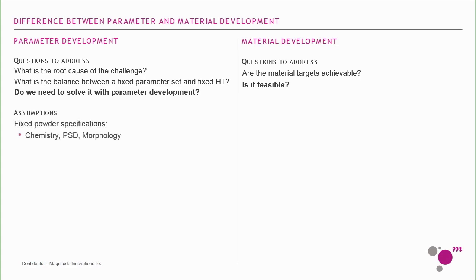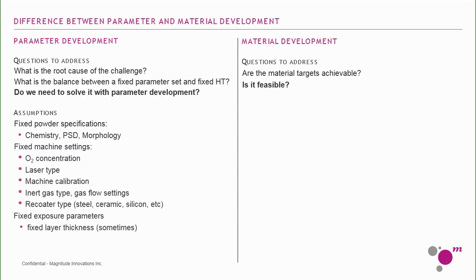So on the parameter development side, we make a couple assumptions, which is that we have a fixed powder in terms of the chemistry, the particle size distribution, the morphology. We have fixed machine settings, which is typically the values that the machine manufacturer sets up, and we obviously don't mess around with, for example, the laser type. But there's also some things that we can optimize and tweak within those confines in order to actually get better material properties, or at least make sure that the material development work is successful. But in terms of parameter development, we leave all that constant.